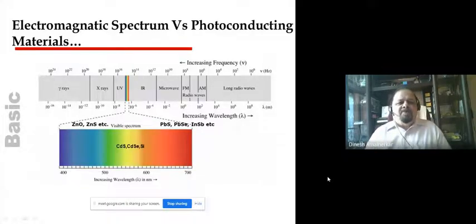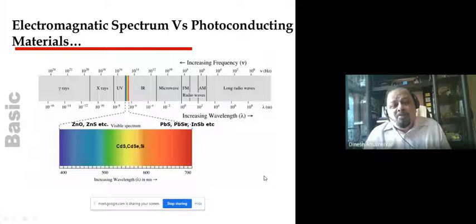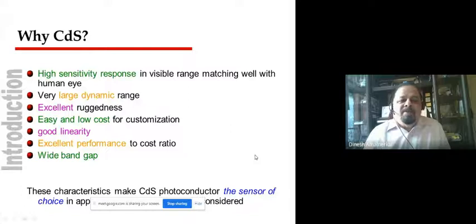Now let us see the electromagnetic spectrum versus photoconducting materials. All materials under the sun can become photoconducting if you have a suitable photon to accept. Because what is photoconductivity? Photon induced conductivity. But commercial photosensors or commercial LDRs of today are exclusively made out of semiconducting materials like zinc oxide, zinc sulfide, silicon, germanium, cadmium sulfide, cadmium selenide, lead sulfide, lead selenide, indium antimonide, and so on. Typically they cover far UV to visible and near IR, something like 300 to 1000 nanometers for commercial applications. Out of all such materials, cadmium sulfide is a material of choice.